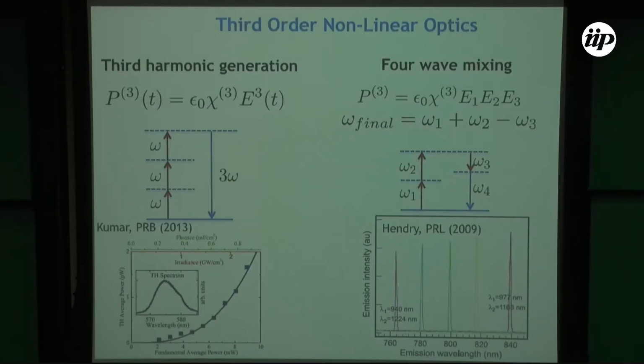So now we move to the third order nonlinear optics part. If you increase one more order, we can have an effect called third harmonic generation. In this case, the induced polarization in your material is going to depend on the electric field to the cube power. You can understand this as your material absorbing 3 photons with an energy omega and emitting just 1 photon with energy that's 3 times the incoming energy. For graphene, people have measured this in 2013, and graphene has a very strong third harmonic generation. The chi3 value of graphene is quite large, in fact.